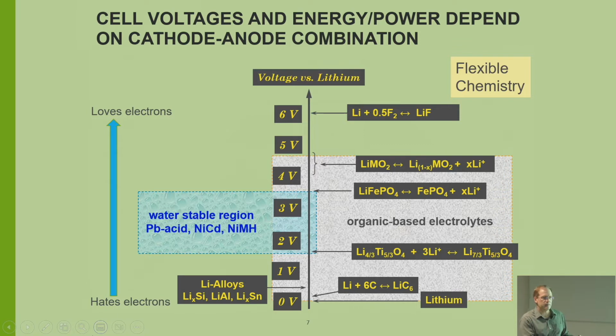Likewise, you can take this cathode material, which I'll talk about later, lithium iron phosphate, LFP for short. It will give up a lithium, and this graphite will take that lithium. Now that difference, 0.1 here and about 3.5 here, makes a 3.4 volt battery. We also have this as an anode, where this can take a lithium. But if you take this LFP and this LTO, lithium titanate, that's one of the most stable batteries around, except for problems with gassing because of the electrolyte, which we won't have time to go into here. That would be the voltage there, and it's really the same voltage as the alkaline battery, so you don't gain a whole lot. But you can get higher milliamp hours per gram in those materials than the alkaline systems, so there are benefits to those systems.